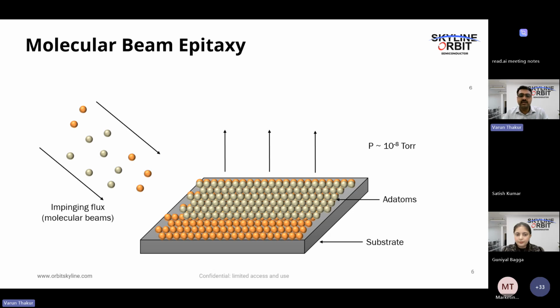A substrate at high temperature helps in the movement of atoms on the substrate and to get a flatter film. As you can see here, I have written the pressure is very low. So this is an ultra high vacuum system. Vacuum systems are classified into low, high, or ultra high vacuum. The growth is typically carried out at a pressure of 10 to the power minus 8 torr.